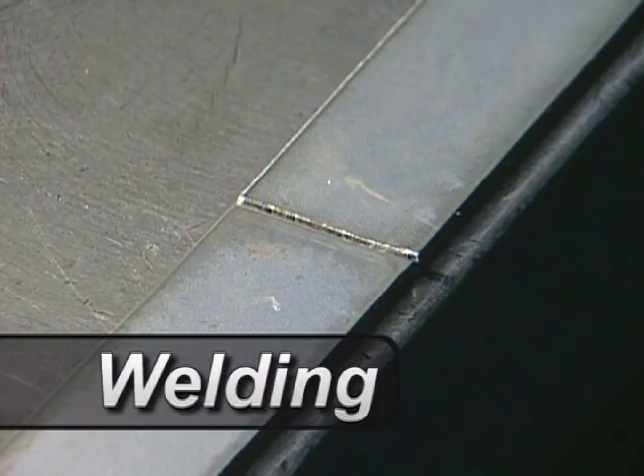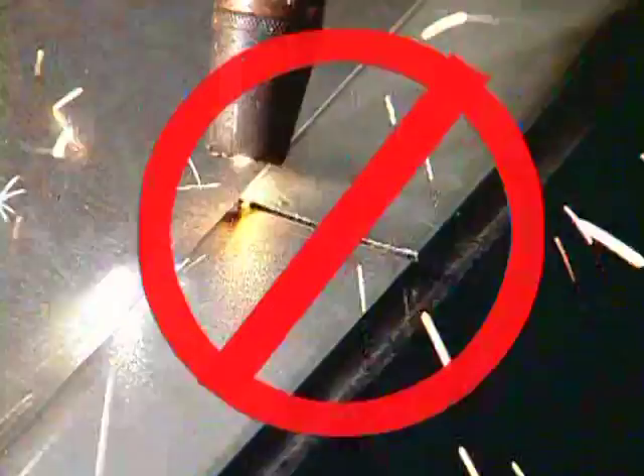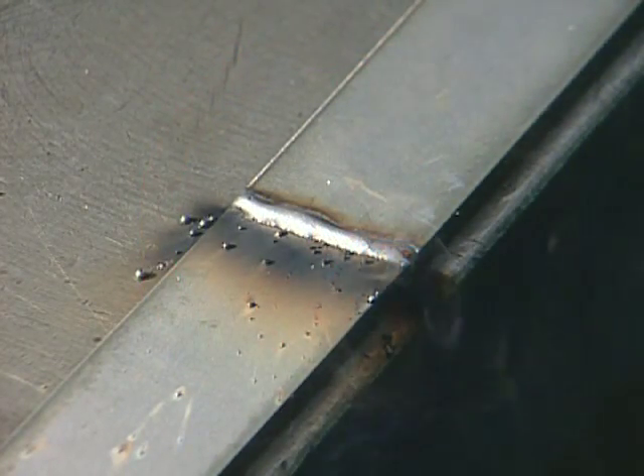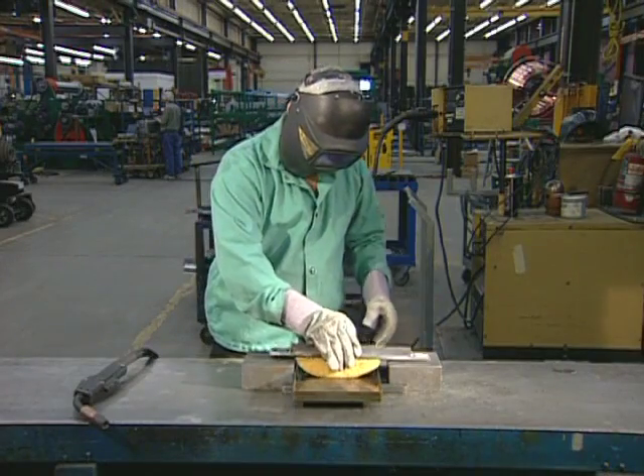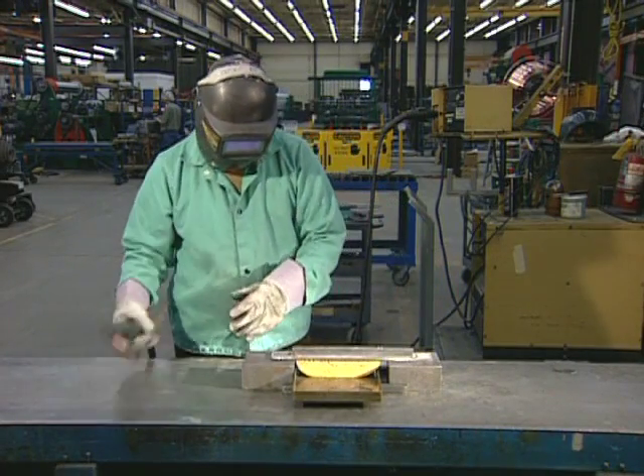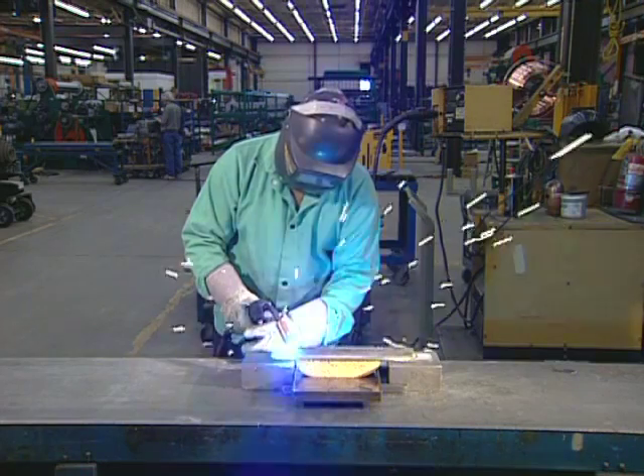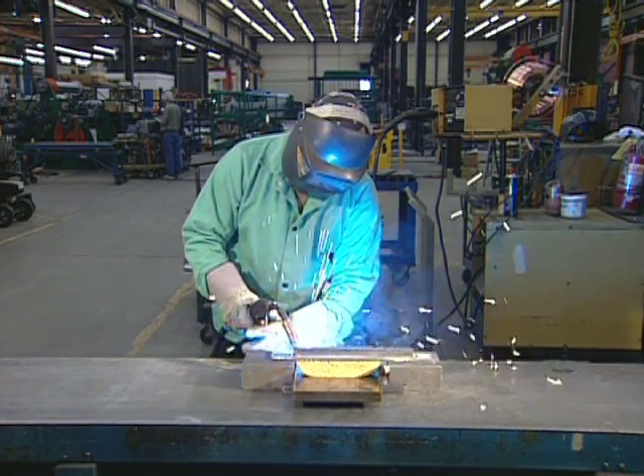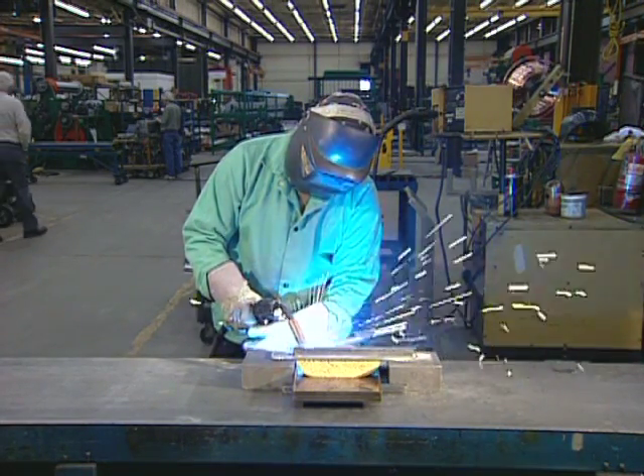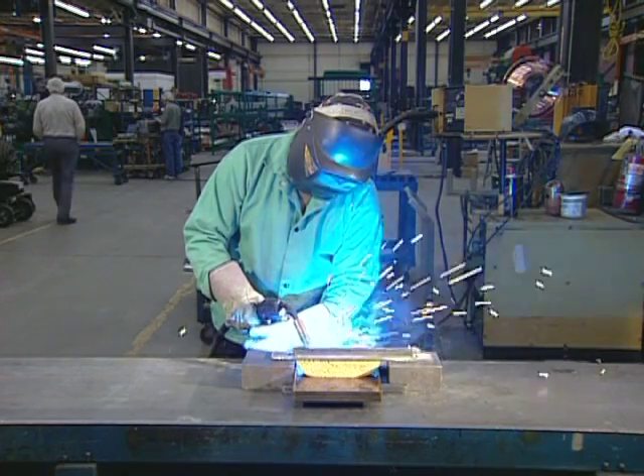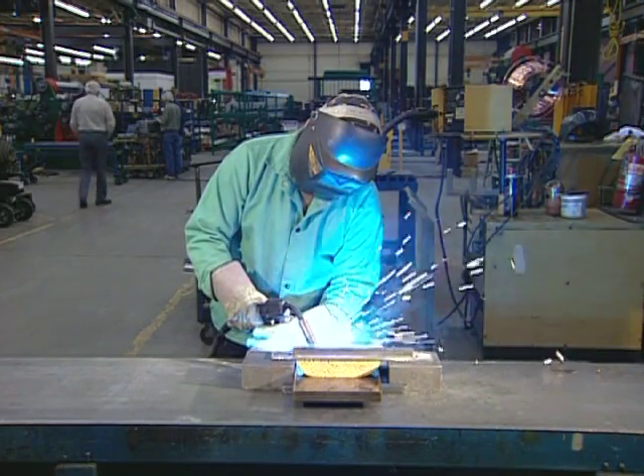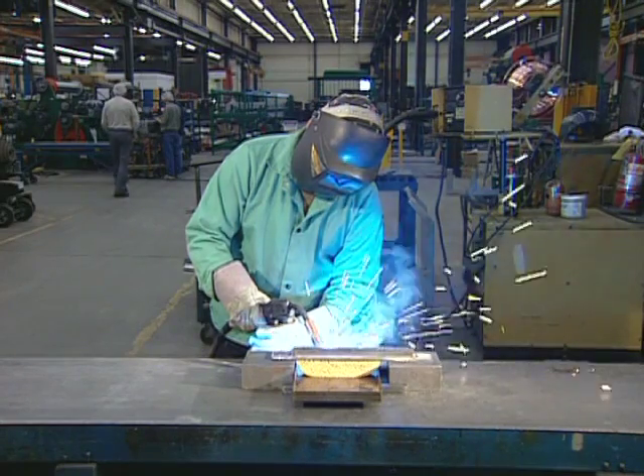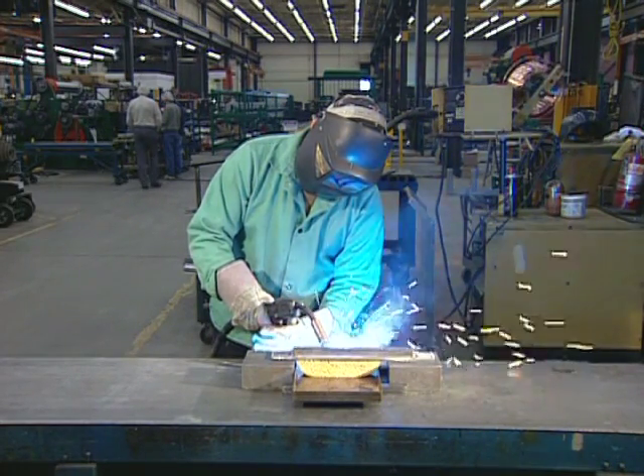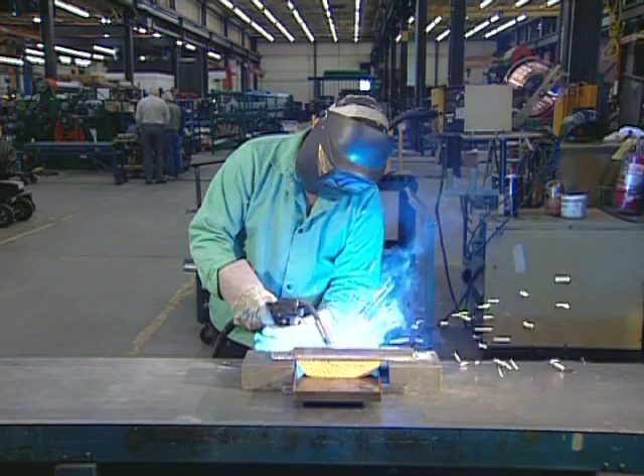Welding. Do not weld directly to the Crodon Wear surface. The weld bond will probably be poor, and the heat will degrade the performance capability of the Crodon Wear surface. When welding is called for, the operator must pay close attention to heat input. When the Crodon Wear surface is heated above 400 degrees centigrade or 750 degrees Fahrenheit, it softens and permanently loses its abrasive resistance. Consequently, MIG or wire welding is the preferred method to minimize heat input.